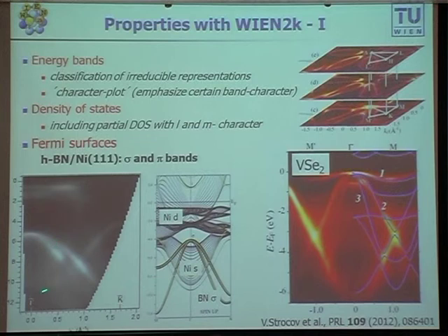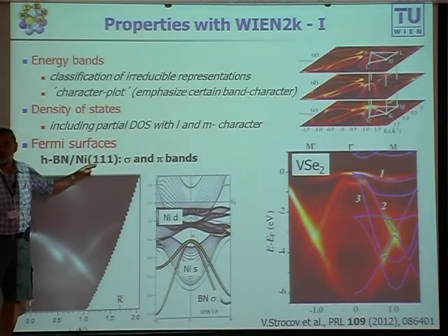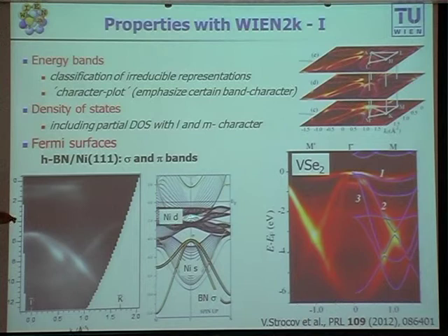And that can be identified as boron nitride bands. Since angular resolved photoemission is very surface sensitive, you see mainly the boron nitride bands and not so much the nickel bands. Only where there is this high intensity of bands, you see something here, but you see the surface bands much more clearly than the underlying nickel bands. So in favorable cases, it works very nicely.